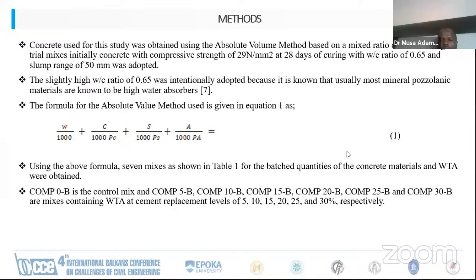So the method we adopted: the concrete used for this study was obtained using the absolute volume method based on the 1:4 mix ratio, using trial mixes initially, concrete with compressive strength of 29 Newton per millimeter squared at 28 days curing with a water-cement ratio of 0.65 and slump range of 50 mm was adopted. The slightly high water-cement ratio of 0.65 was intentionally adopted because most mineral pozzolanic materials are known to be high water absorbers.